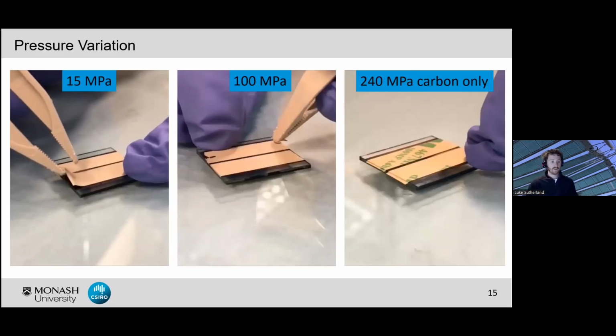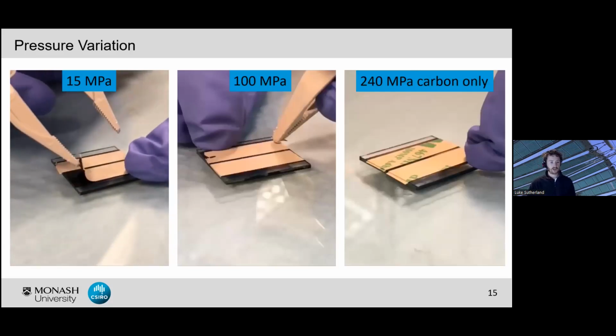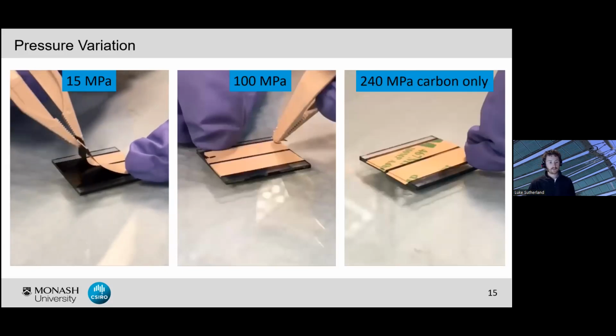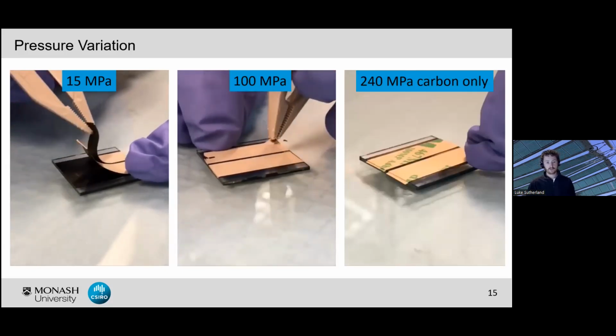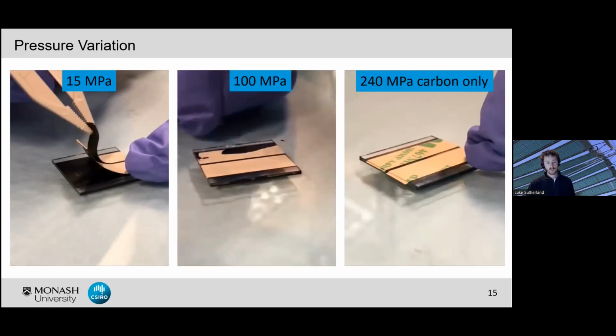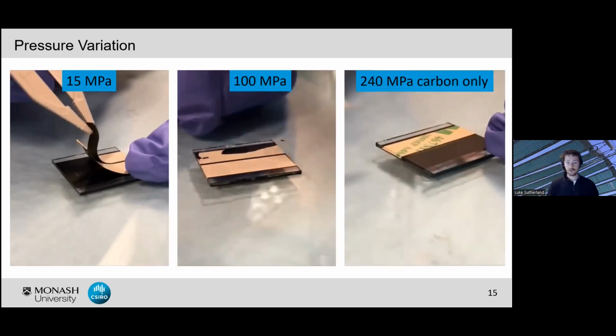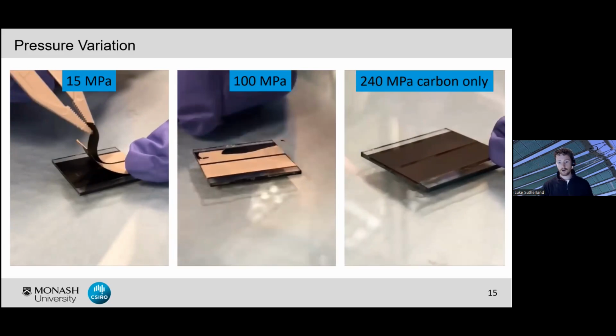And we see this again, just a couple of little videos here just to show 15 megapascals too low. The electrode peels off very easily. 100 megapascals, we get better connection, but if you do some destructive analysis, you can very easily peel off the electrode. And then 240 megapascals, this was for a carbon only electrode. You can very easily peel off the release layer and it's stuck very well. So it's actually very hard to delaminate from the device without actually completely destroying the underlying layers as well.